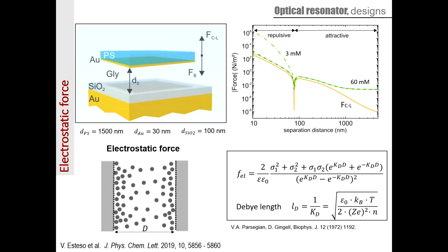We also analyzed the effect of potential electrostatic forces occurring in our system, and for this we implemented the Poisson-Boltzmann methodology. We considered what happens if we include a monovalent salt diluted in the glycerol, and we observed that for large enough concentrations of this salt, the response is basically the same, whereas if the amount of salt is not enough, then we will have an additional repulsive component.